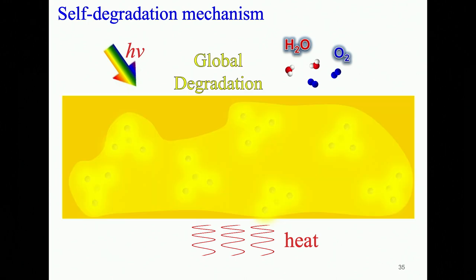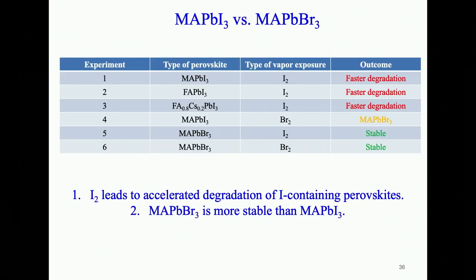In this study, we not only look at the MAPbI3 perovskite, but also look at many other kinds of perovskite materials. What we find is that for all the perovskite materials that contain iodine, the iodine vapor exposure leads to faster degradation. But when we performed similar studies on the MAPbBr3, that is replacing the halide composition in the perovskite structure